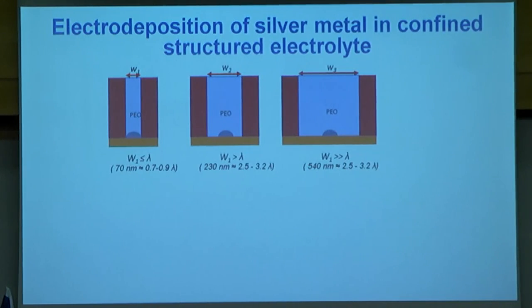So what we wanted to do is take lambda critical now and really confine it to our block of polymer, to make blocks of polymers with different sizes, a little bit smaller and smaller and smaller. So we started from big on the right, really much bigger than lambda critical, then a little bit lower, and at the end we made it smaller than the splitting, than the instability size.